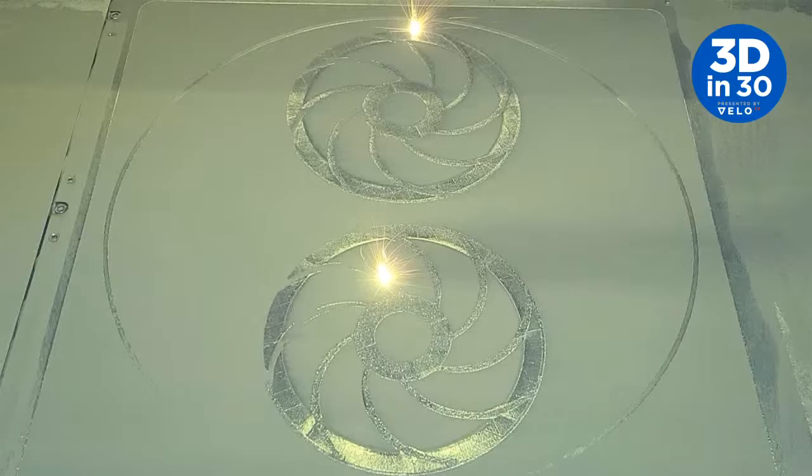That's because as you heat up gas, that changes the index of refraction, which then causes distortions in optics as light rays pass through it. Same thing happens in the powder bed fusion system. You have a hot gas coming above the powder. That changes the index of refraction there. That changes how the beam is converging down to your workpiece. And if you don't effectively clear that out, you can have your beam change shape in the middle of laser processing your part.